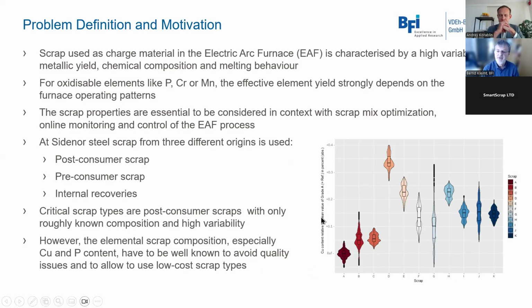So you can see here in this figure, for example, the copper content of different scrap types. And you can see that for some scrap types, the scatter in the composition and the copper concentration is very high. These are the post-consumer scraps where the copper content can vary in a range of 0.1 to 0.2%, and this makes it difficult to use them in higher amounts because copper and phosphorus content have to be well known in the scrap types to avoid any quality issues, and that means you have to know these contents very exactly to allow to use also higher amounts of low-cost scrap types.